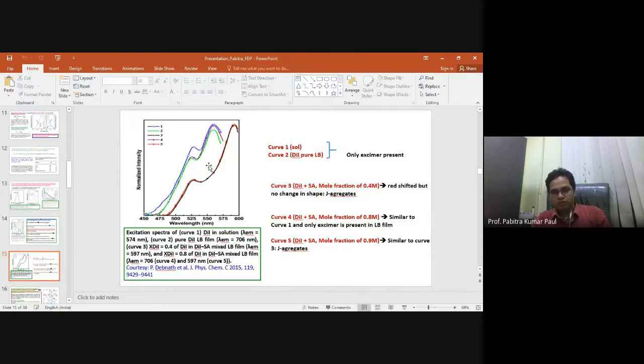So for 1 and 2, here you see the blue and the green color, one is for solution and another is for LB film, but no stearic acid, no matrix, only the pure component LB film. So only the excimer band is present, because this is very similar to the solution excitation spectra, and very similar to the solution absorption spectra.